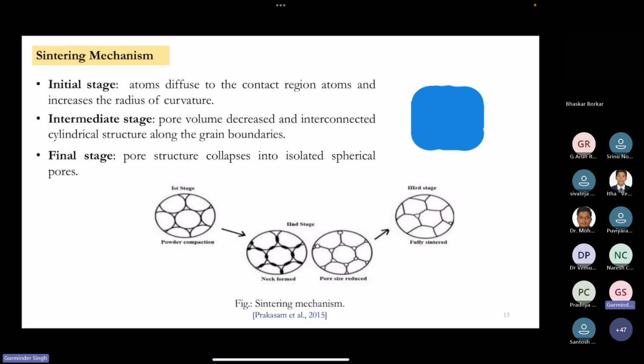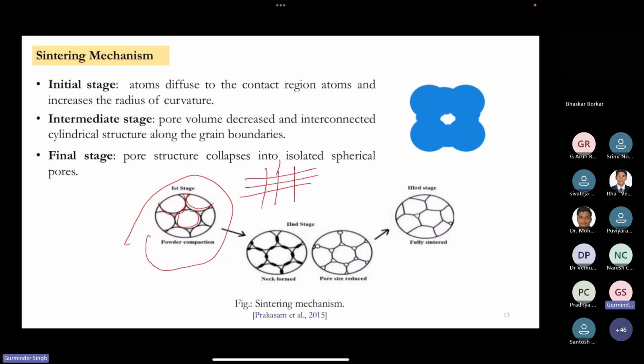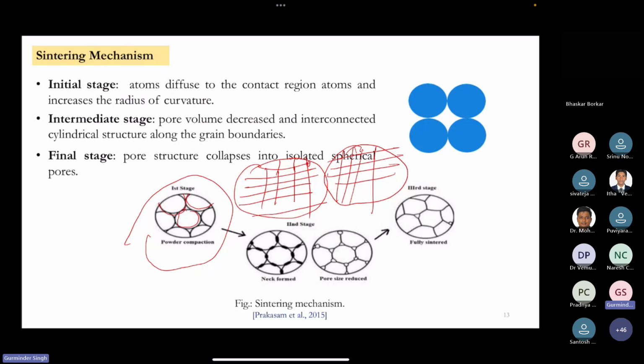The important thing to understand is the mechanism of sintering. Sintering, everyone knows, is a fundamental process in manufacturing. Any manufacturing processes book covers powder compaction, where powders, which have a spherical or irregular shape, come together when you heat them up at a high temperature. Due to the thermal energy, the atoms at the corners of the spherical metal balls will be excited, and they will try to lose energy by making bonds with nearby atoms, and it will create a neck starting from the nearby region of the metal particles, and it will grow, and later on it will look like this.